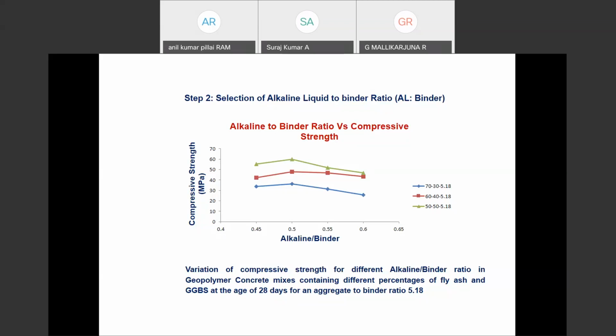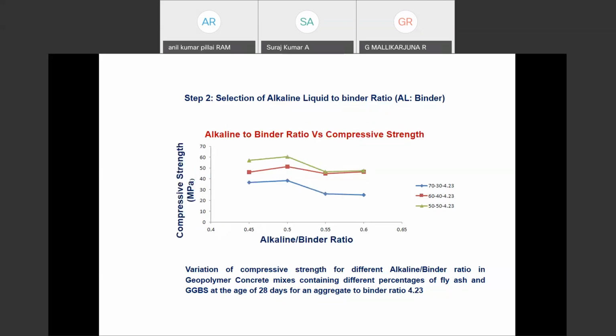And we have prepared the charts for both the outdoor curing and oven curing. Anyone can select based on your workability requirement. You can select the values for production of the strength there. And this is the alkaline to binder ratio, the aggregate to binder ratio effect as 4.23. And here the fly ash has 70% and GGBS has 30%. And here the fly ash 60-40 and 50-50 we had considered.